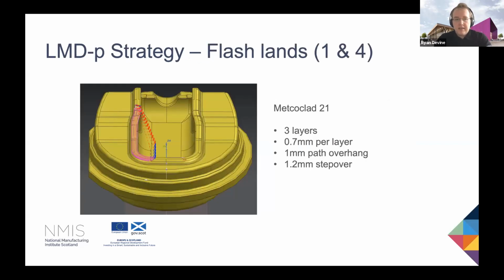So for looking at then the reconstruction of the die, the deposition part with LMD, for Flashlands 1 and 4, they were essentially mirror images of each other, 3 layers at about 0.7 millimeters high each. We had a 1.2 millimeter step over between paths, and we also had a 1 millimeter path overhang. And this was just to ensure that we built up a sufficient amount of material that it could then be cut back to nice final geometry that was within all the tolerances required.